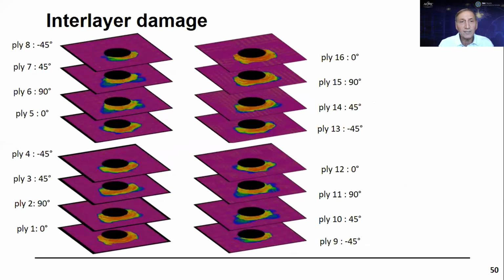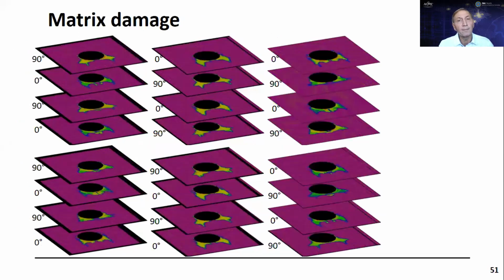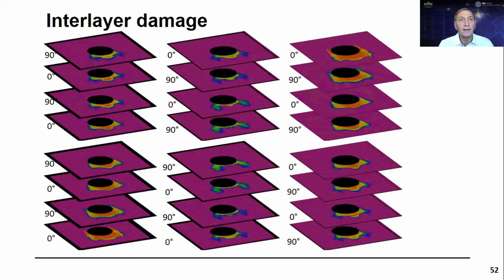And here, what you see is, of course, a lot of the delamination and matrix failure takes place near the contact region, where the bolt comes into contact with the laminate. But before I superimpose these, I move on to the second case where you don't have any 45-degree plies. I'm looking at matrix damage in each ply. And again, it's close to the region where contact takes place between the bolt and the laminate. And the interlayer damage is similar to what I showed before.